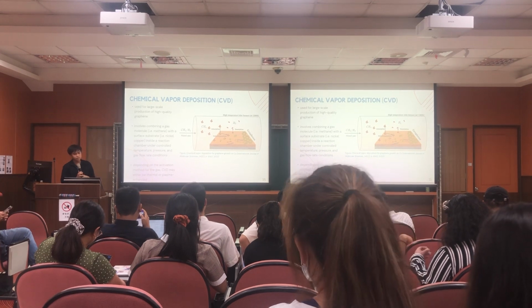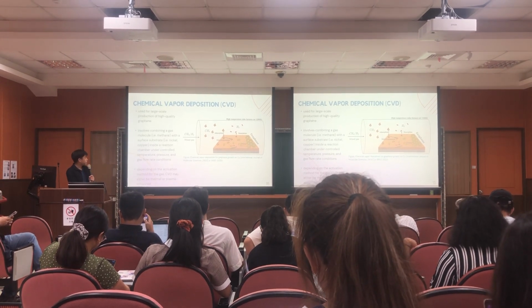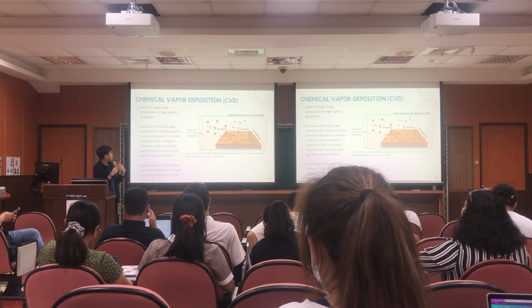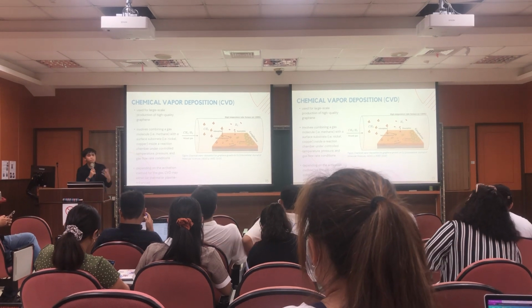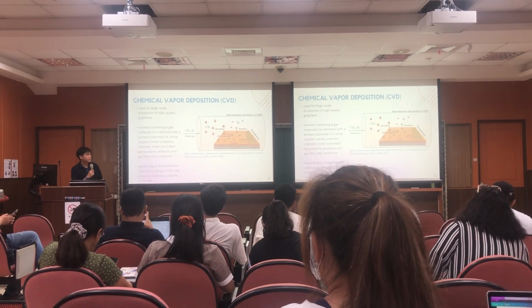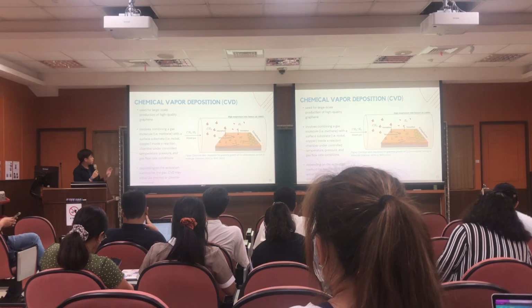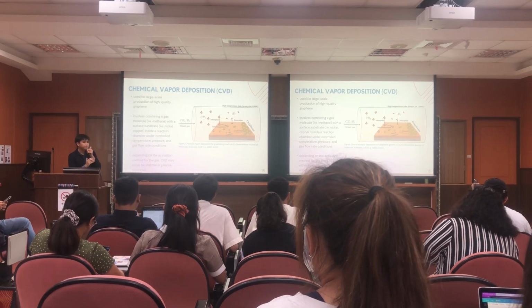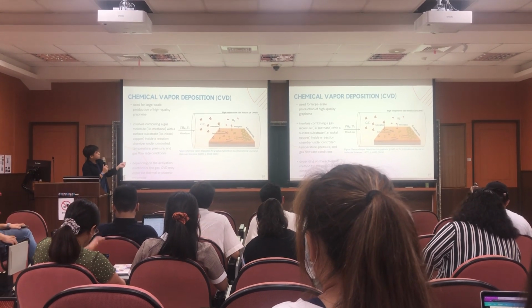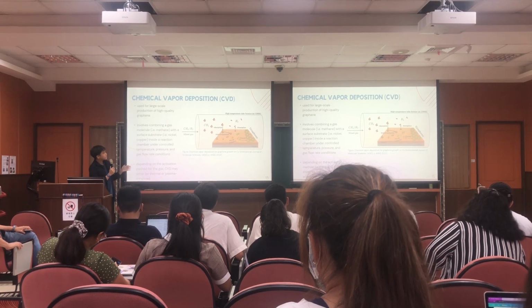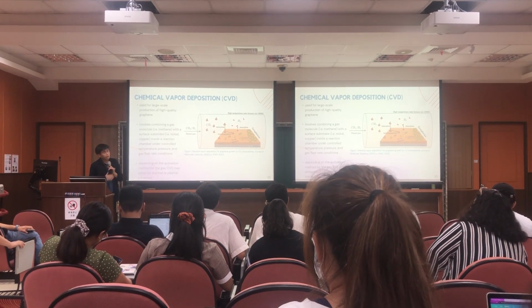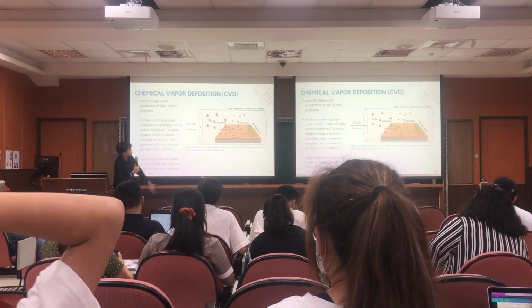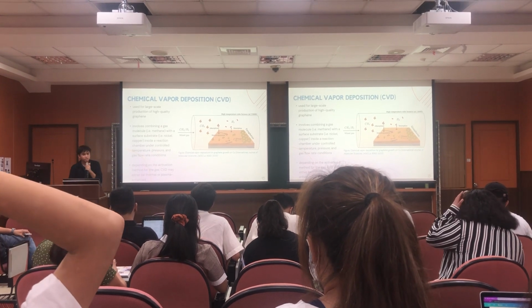Depending on the activation method for the gas, CVD may either be thermal or plasma enhanced. So in thermal CVD, the decomposition of the gas is based on the heat that you apply to it, while in the latter, you use plasma to excite the ions in the gases so that they are more reactive. And because of that, your graphene grows on top of the copper catalyst.